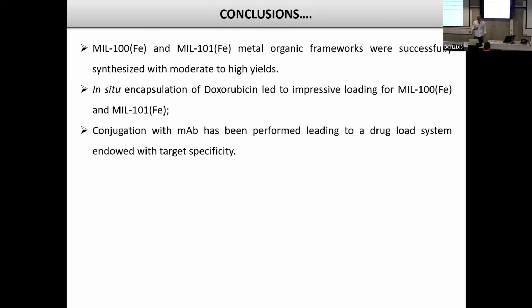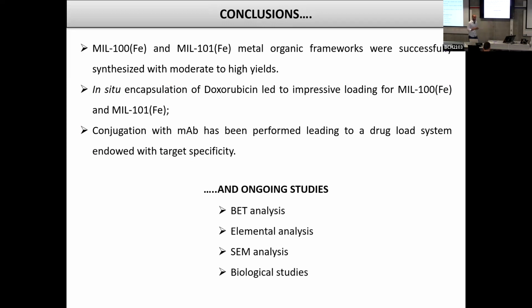So, in conclusion, we synthesized these two systems. We were able to load a high amount of doxorubicin, and in situ encapsulation was useful to reach this goal. However, we have some ongoing studies. The first is BET analysis, because if doxorubicin has been included inside the system, we should have a reduced superficial surface area. Elemental analysis is fundamental to confirm the real amount of doxorubicin included inside the MOF.